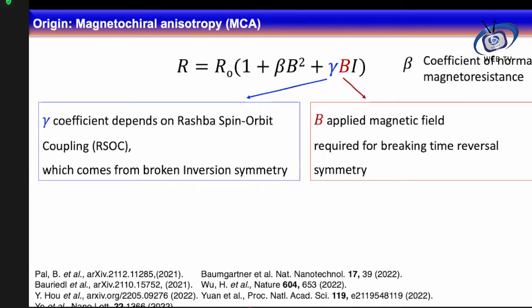But for this gamma function, as I already explained in the last structure, they intentionally developed an asymmetric structure where the inversion symmetry is broken. In that case, we would have spin orbit coupling, and this gamma coefficient in principle depends on the spin orbit coupling. So you need these two broken symmetries: number one, the inversion symmetry, and number two, the time reversal symmetry. Both must be broken. Then you would have this chiral magnetoresistance.